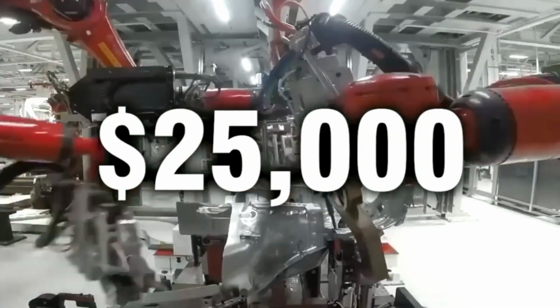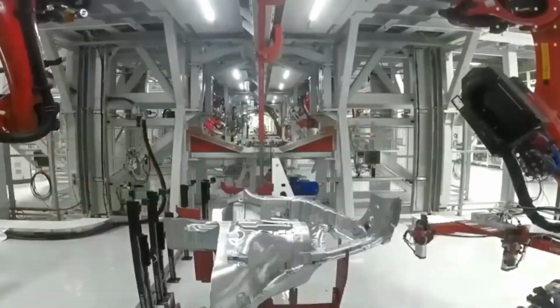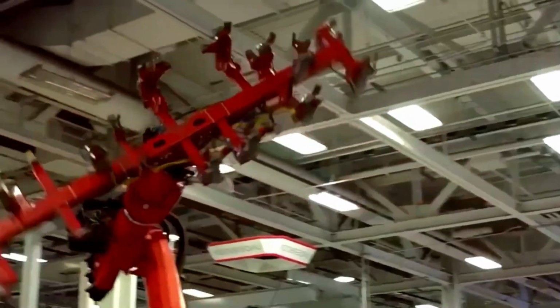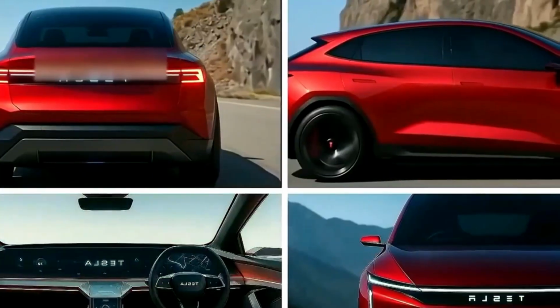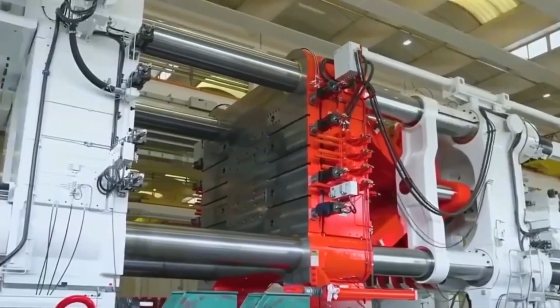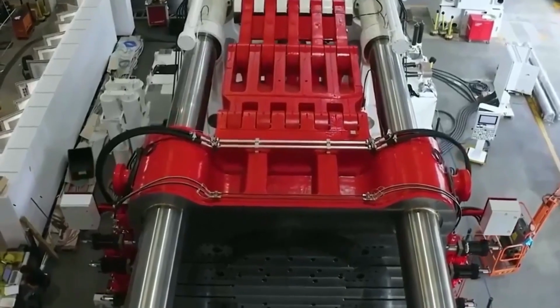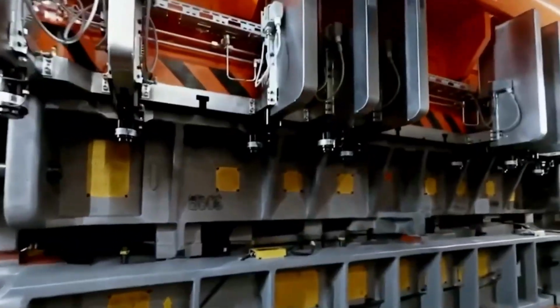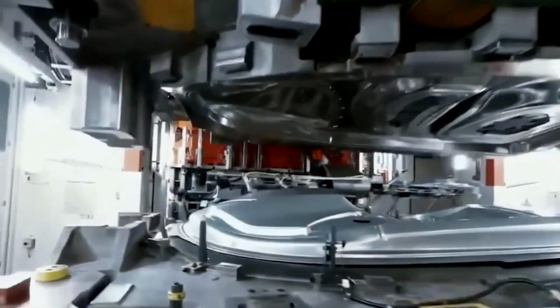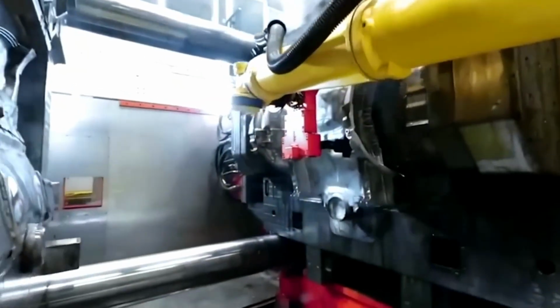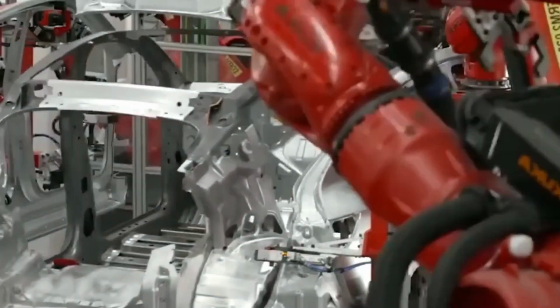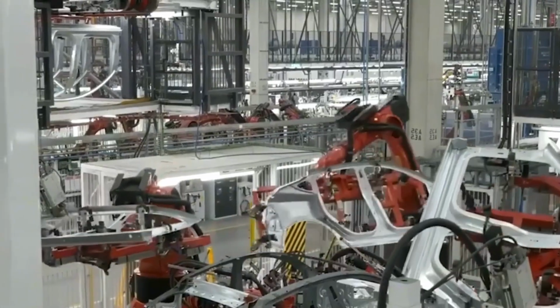Molten aluminum is driven into the mold cavity at enormous force, and from that point forward, everything happens within seconds. The margin for error is nearly zero. Inject the metal too fast and trapped air or turbulence creates internal defects. Inject it too slowly and the aluminum begins to solidify before the mold is fully filled. With a component this large, a single section that fails to fill correctly turns the entire part into scrap.